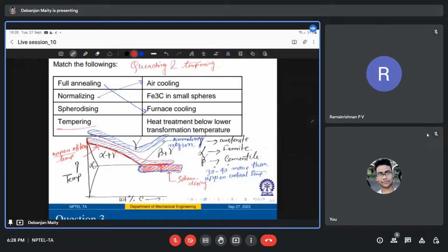So what happens is like this: quenching basically comprises a rapid cool from a high temperature, right? So a ferritic steel would be heated to above the upper transformation temperature, or what I am calling the upper critical temperature, and then it gets quenched in water or maybe oil or air blast, to produce a very high strength fine grained martensite, right? But these steels are never used in the quenched condition. They are always tempered following this quenching operation.